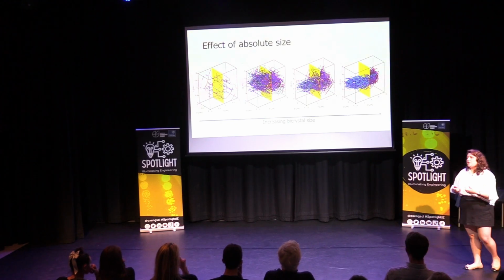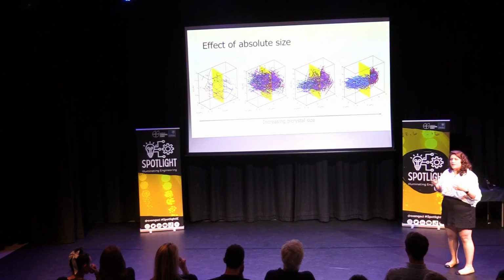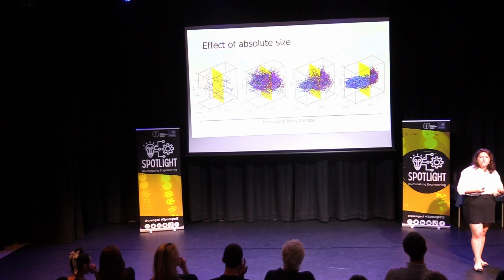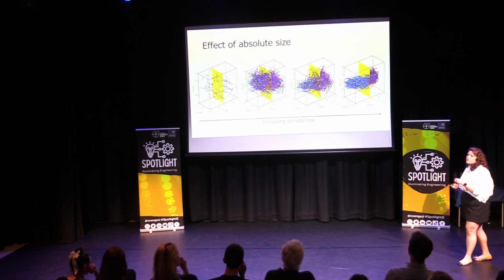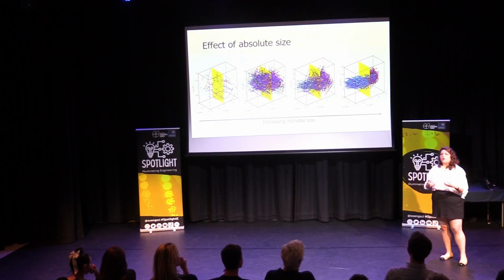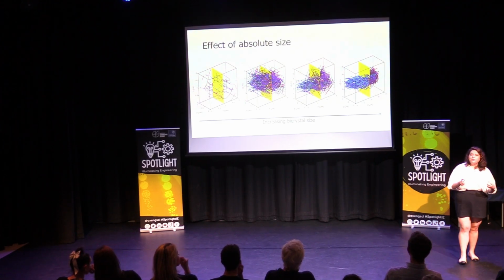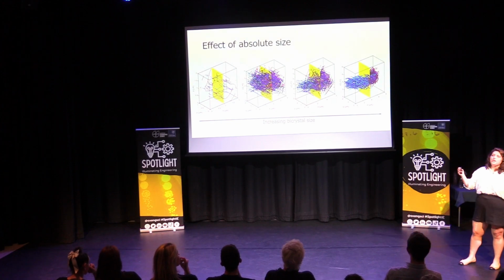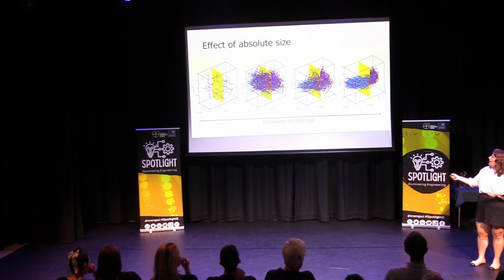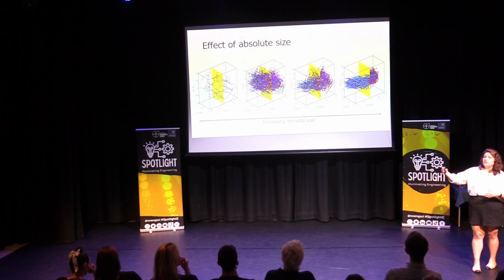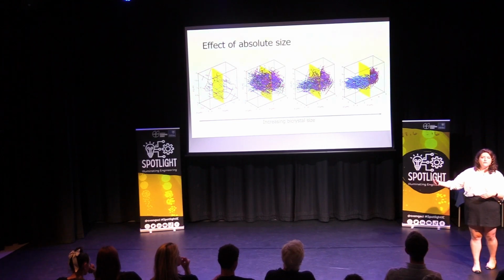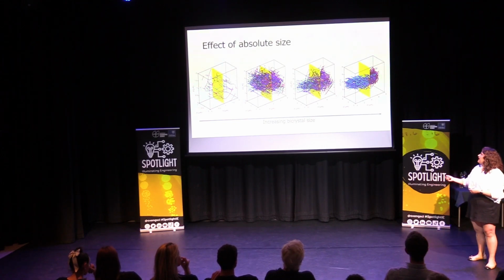What happens if we change the crystal sizes themselves? The grain size in a material is incredibly important. As a rule of thumb, the smaller the grains in a material are, the stronger it is, but the harder it is to bend before fracture. The bigger a grain is, the more time there is for dislocations to build up in it, so it's much easier to bend, but it's less strong. So the idea that we have to look at not just the dislocation motions themselves, but how they interact at a particular size scale is incredibly important.